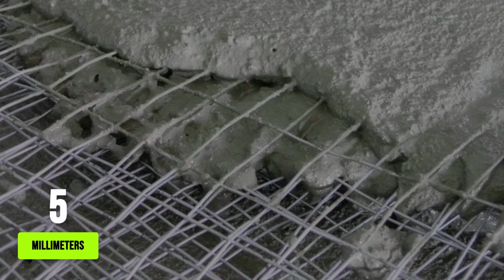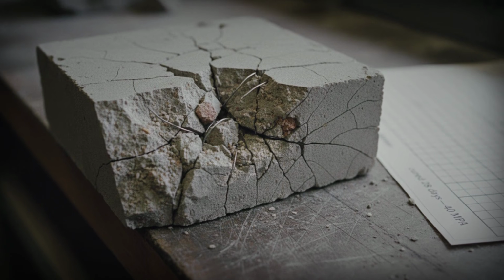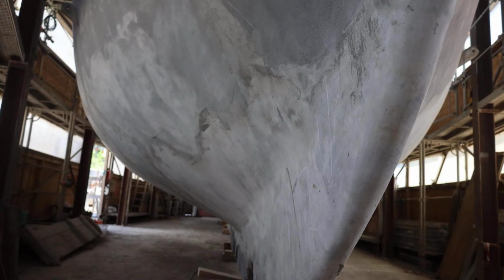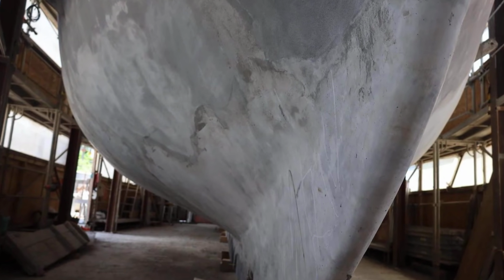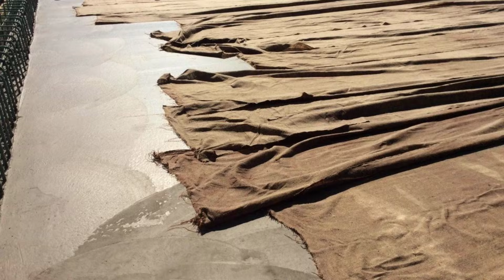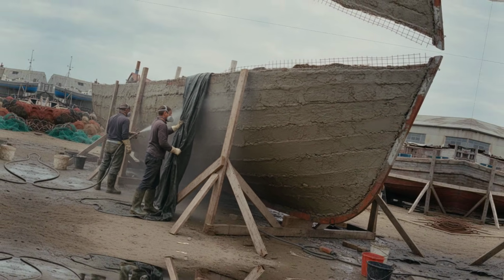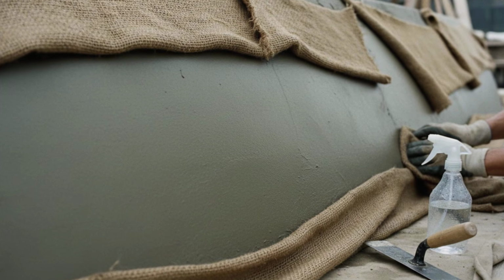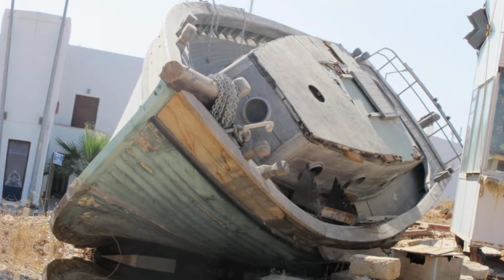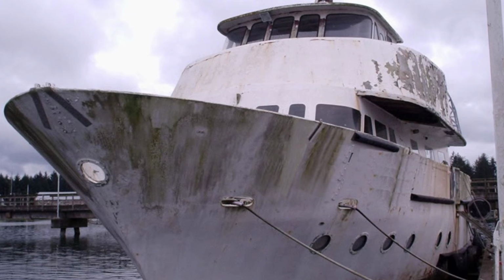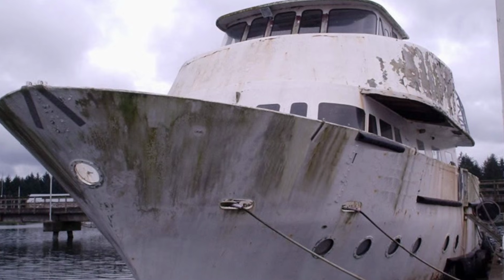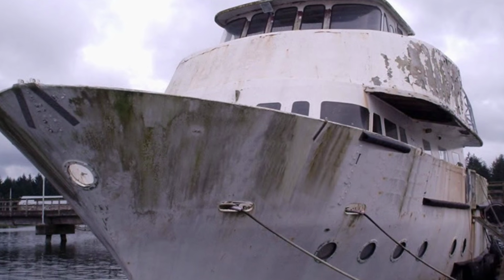Cover depth is a hard rule. At least 5 millimeters of mortar must shield every strand of steel from salt water. Less than that, and rust will bloom within a season. When done right, the shell reaches compressive strengths over 40 megapascals, stronger than most city sidewalks. But the work is not finished when the last trowel is set down. The hull needs to be kept damp for a week or more, wrapped in wet cloth or sprayed with water. This slow, moist cure locks in strength, preventing micro cracks and sealing the steel away from the ocean. The result is a dense, unified barrier. No voids, no shortcuts, just raw, engineered durability.